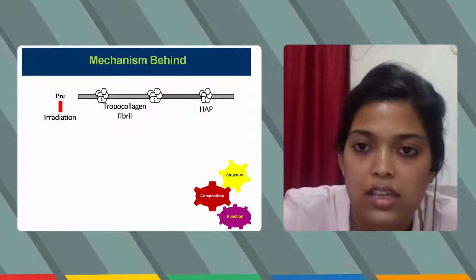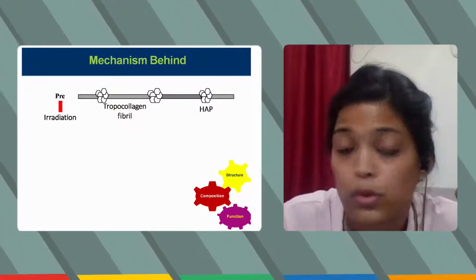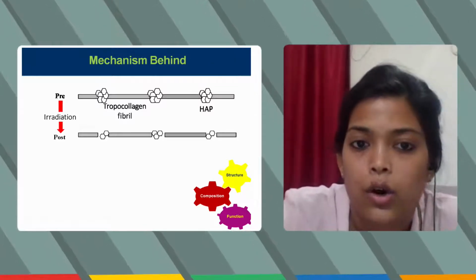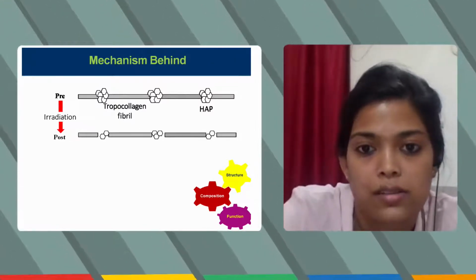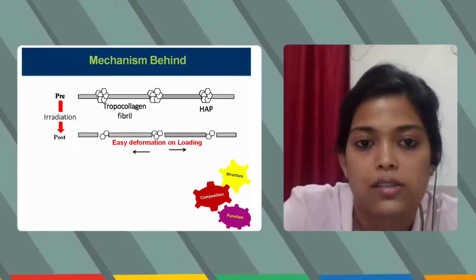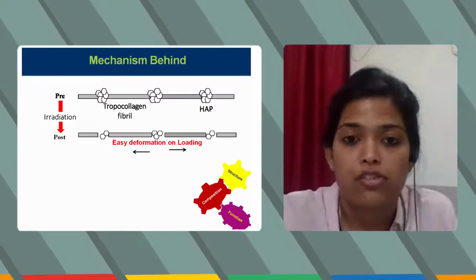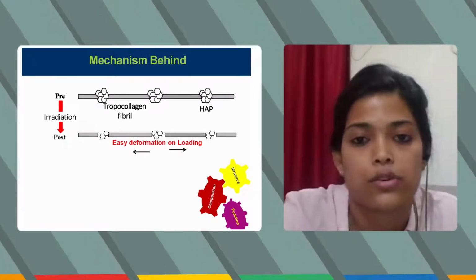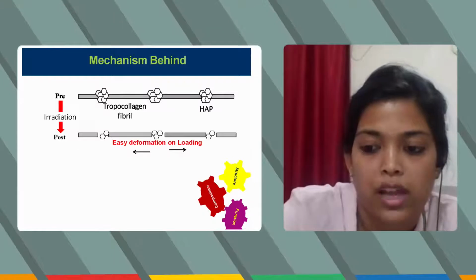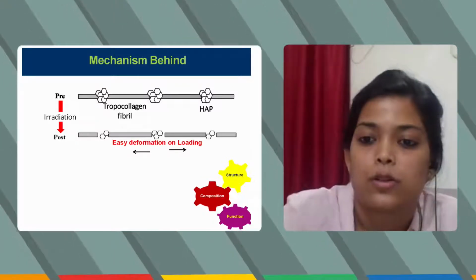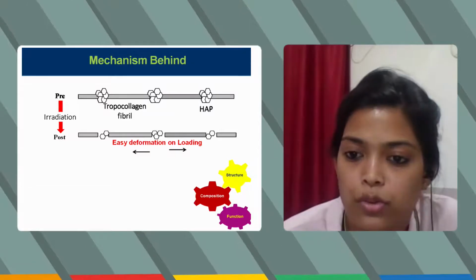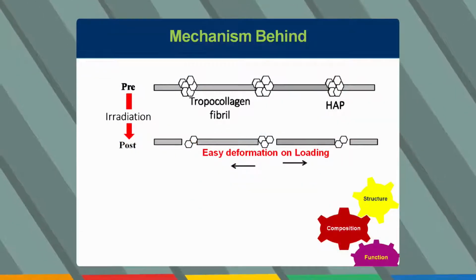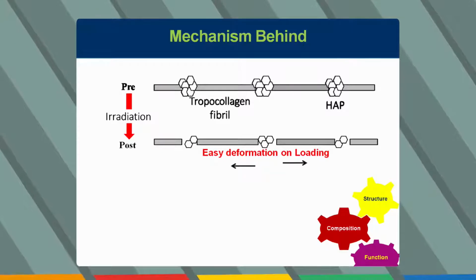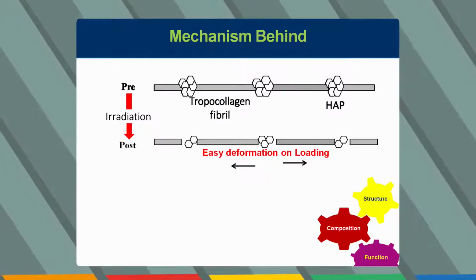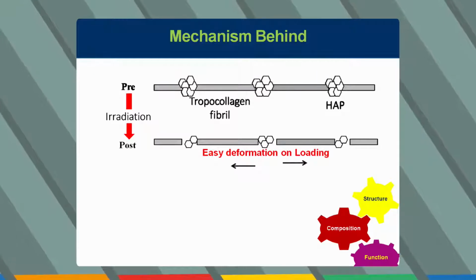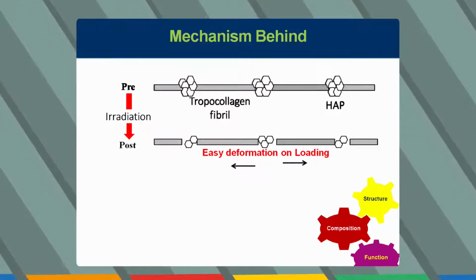When it comes to post-irradiation, all the mineral content is lost. So these collagens are now easy for sliding. This gives us deformation on loading, since there are no mineral particles at the collagen to collagen interface. So bone is a material which responds coherently between function, composition, and structure. If any one of them changes, like if function changes, composition will definitely change, structure will definitely change. If composition changes, both the other things will change.